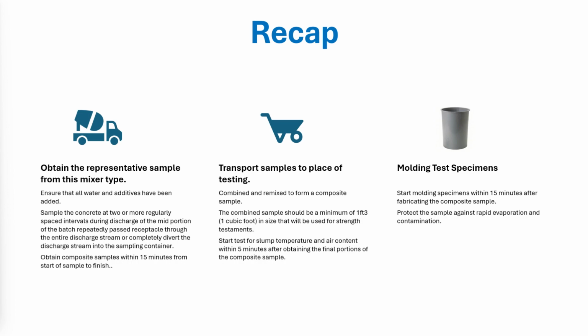Molding test specimens. Start molding specimens within 15 minutes after fabricating the composite samples. Protect the samples against rapid evaporation and contamination.